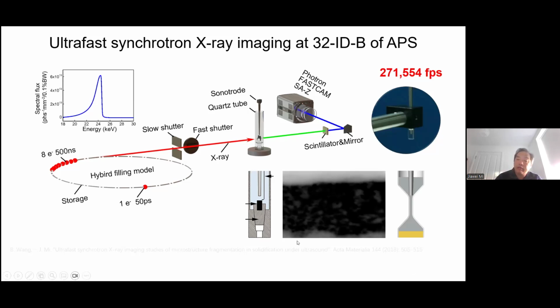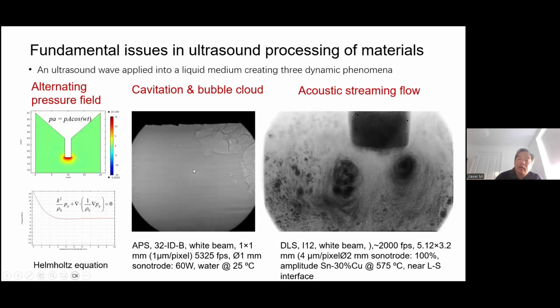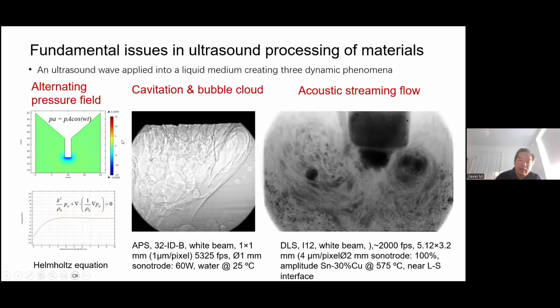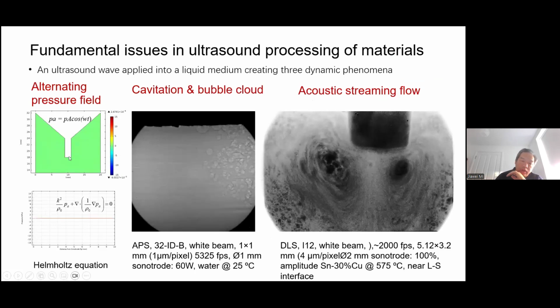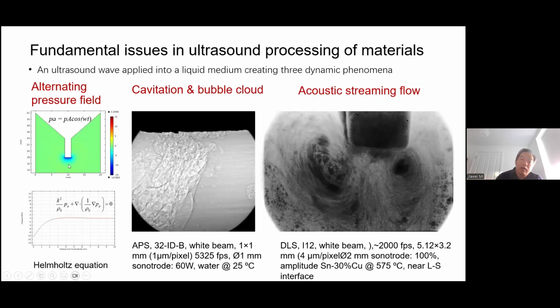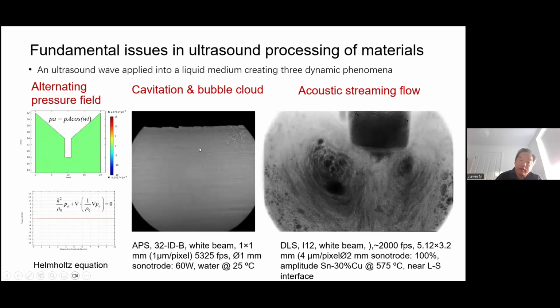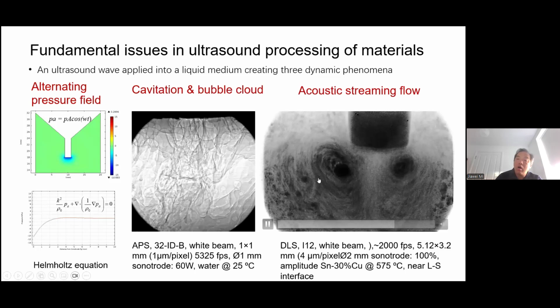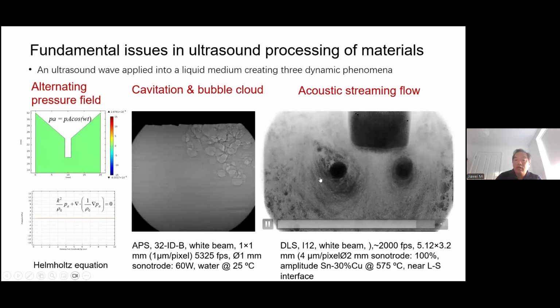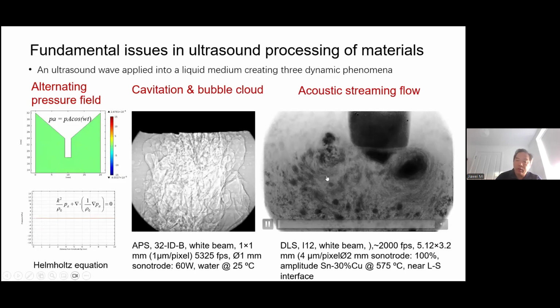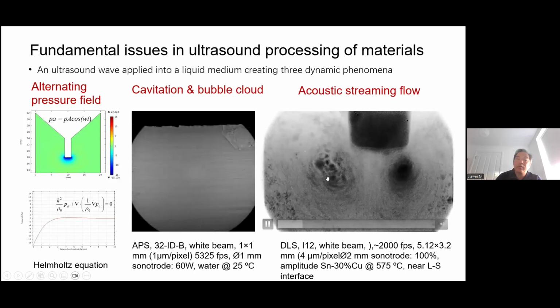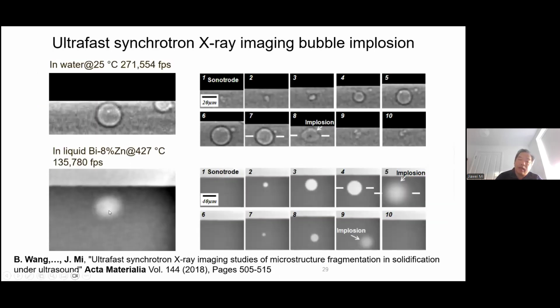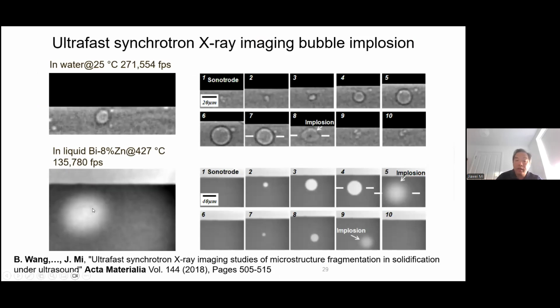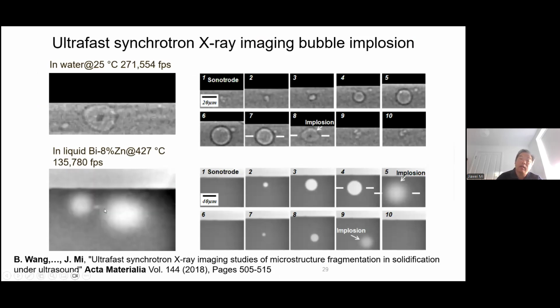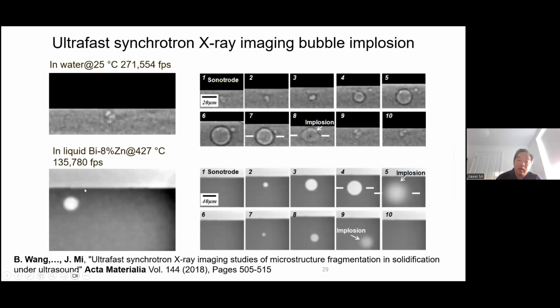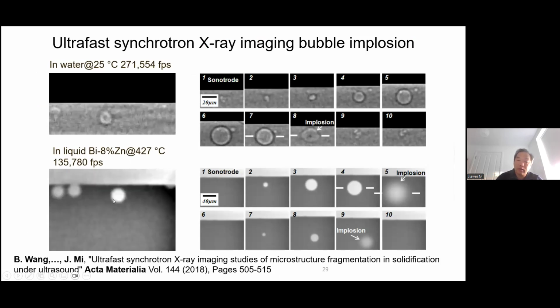And you can clearly see the vibration of the tip. We are more interested in understanding the ultrasound capability when it transmits the sound wave into the melt, how the sound wave changes the structure, how the cavitation changes the structure, how a strong streaming flow can change the structure. So those are the three fundamental issues when you're using ultrasound to process any type of material. So I'll give you an example. If you have cavitation and a cavitation bubble growing and imploding, that implosion is clearly captured by the ultra-fast X-ray imaging.